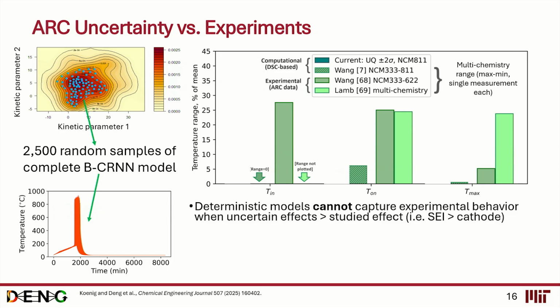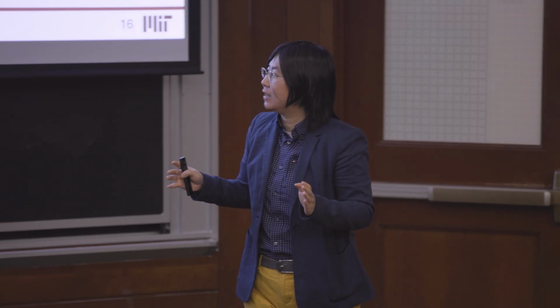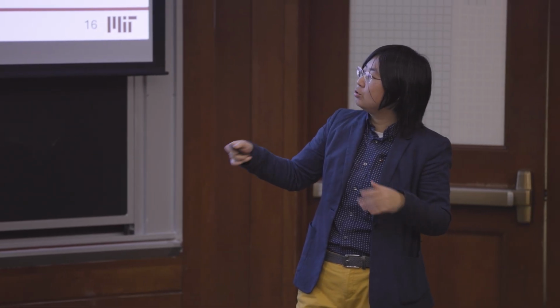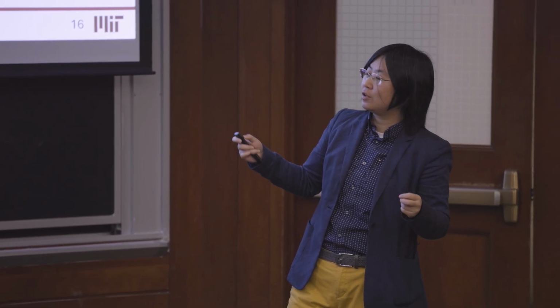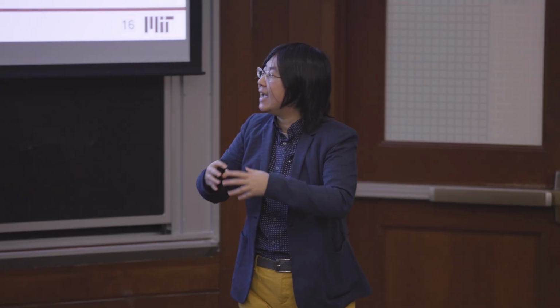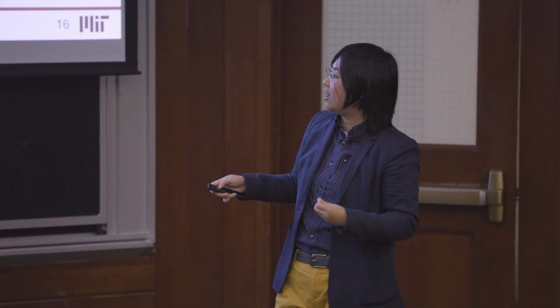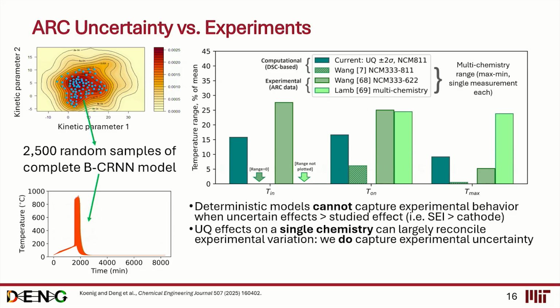This tells us the importance of considering the variations in the experiment, and the result of deterministically modeling the chemical kinetics. Now that we are able to capture the uncertainty, we would also be able to simulate all the cases with all the possible chemical kinetics. So this is what Ben did, a lot of random samples of the possible chemical models, so that in the end we have an ensemble of the predicted dynamics of a single cell put into this ARC experiment. And the dark green is what we get. We can roughly capture the dynamics, and especially the variation across the literature, why across different chemistries we have different sensitivities in the three metrics.